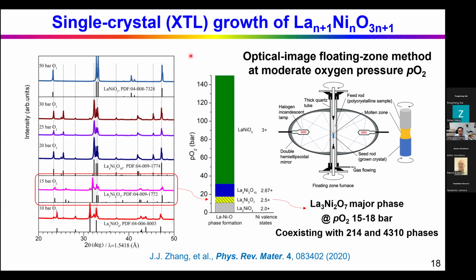The single crystal of this Ruddlesden-Popper nickelate can be grown with the optical image floating zone method under different oxygen pressure. According to this paper, you can get different phases at different oxygen pressure.